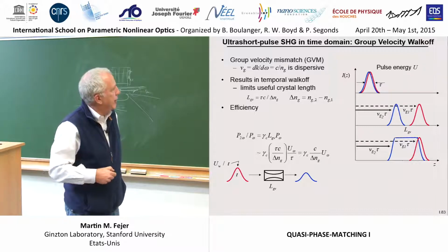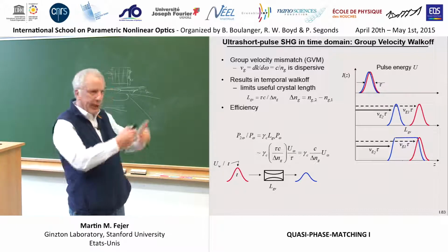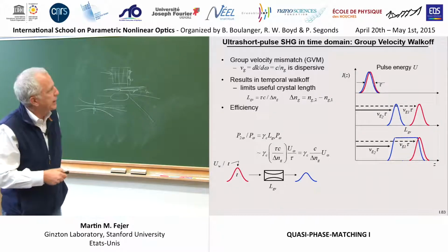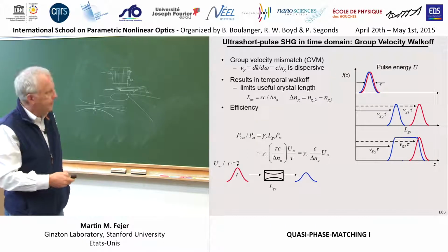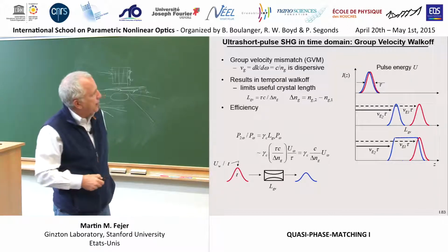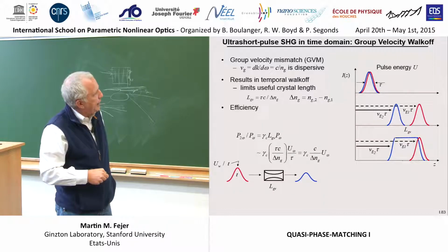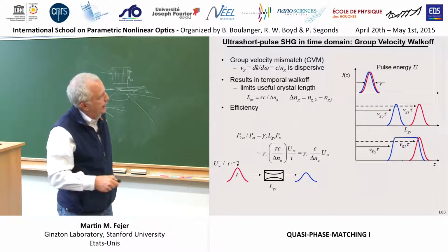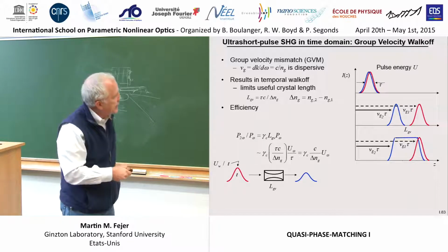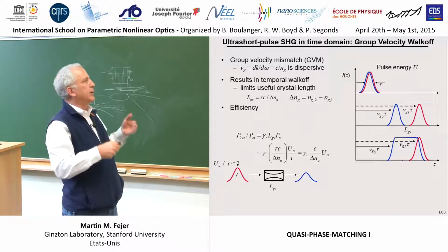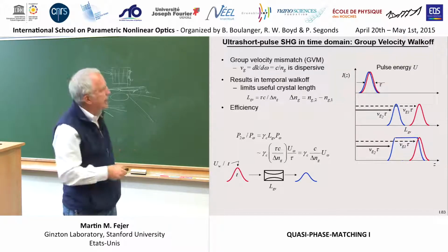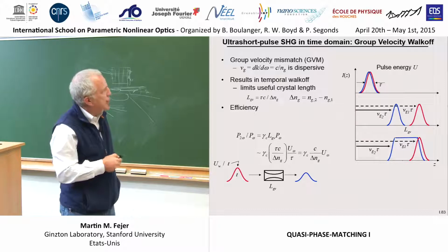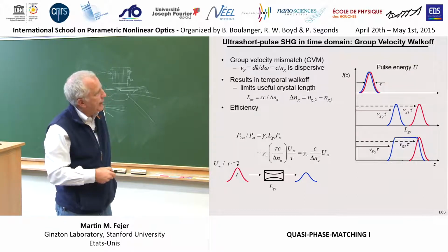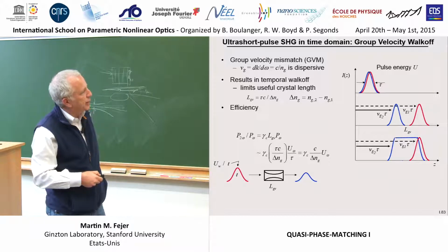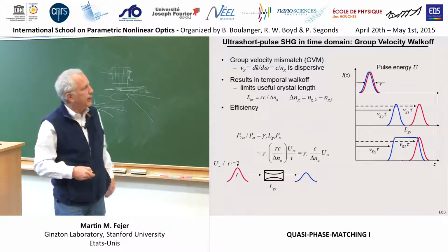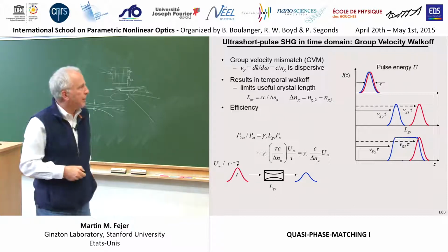If we make the length of the medium this walk-off length, the characteristic length where you preserve the duration of the pulse, so it scales like we just discussed. Then, if you look at how this works out, the increase in usable length for long duration pulses is exactly canceled by the lower peak power as you make a longer pulse. And so this mixing efficiency, when you choose this optimum length for a given pulse duration, is independent of the pulse duration and is a function only of the pulse energy and the mismatch in the group indices, which is interesting.